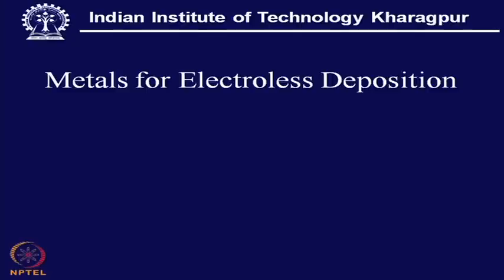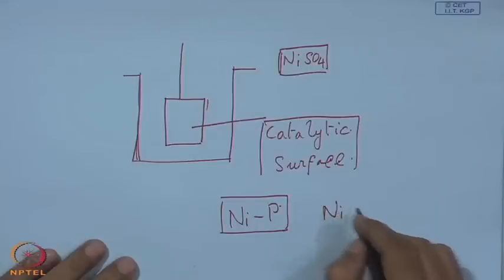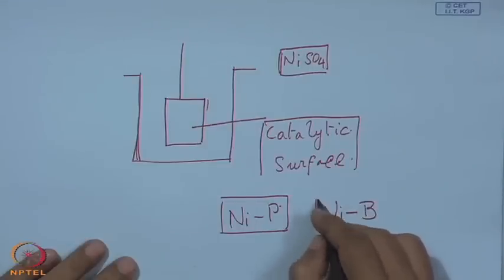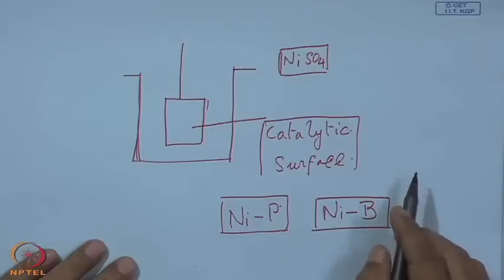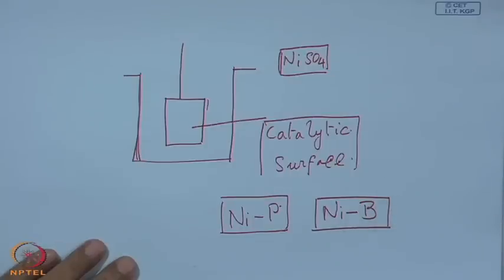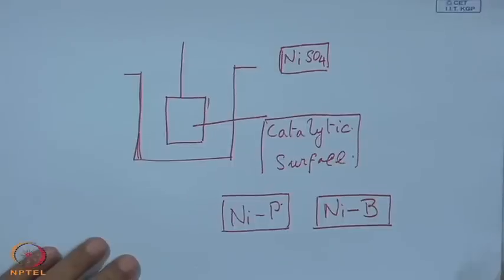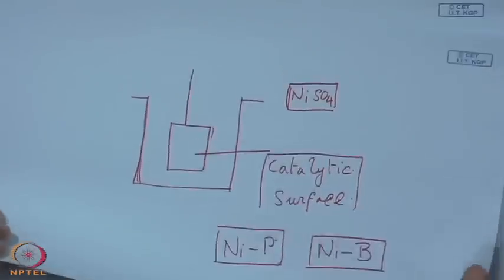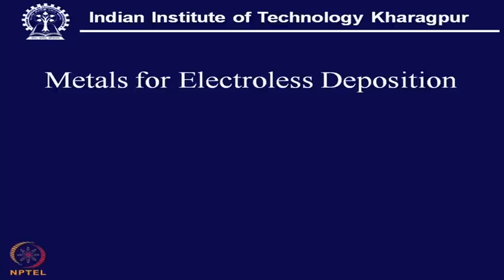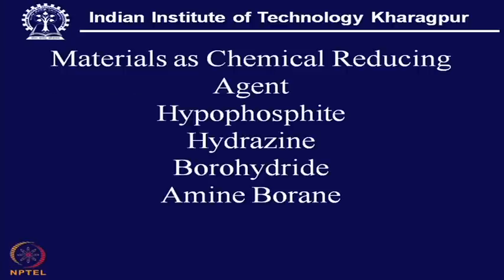a reducing agent containing boron, it is not difficult to have nickel boride also, and in this case the reducing agent is not a phosphorus containing element, but a boron containing element, and as a result we have nickel boride. So, materials as chemical reducing agent: it is hypophosphite that we have mentioned, hydrazine, borohydride, and from that we get this boron for this nickel boride. It is also amine borane, that is also a source of